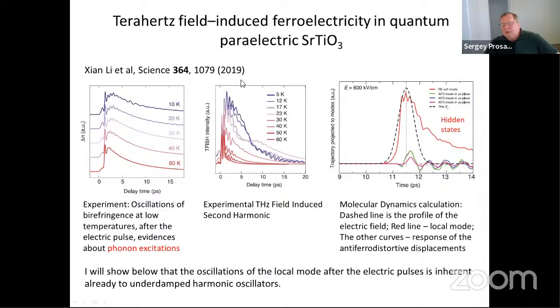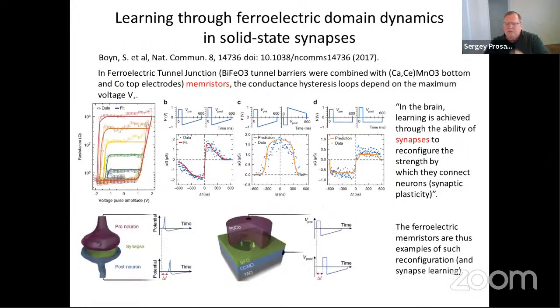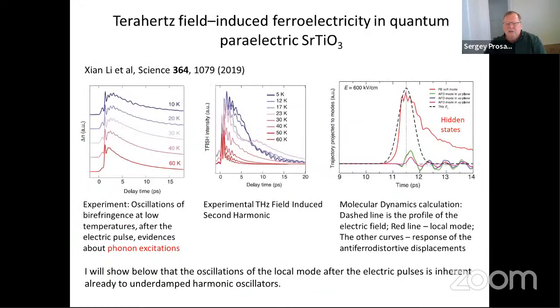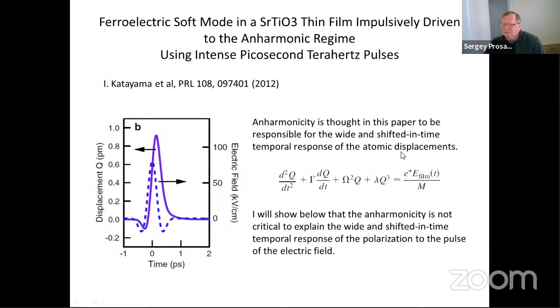But in our case, like in memristors, we apply some limited number of pulses, and we are not in the ferroelectric phase and not in the relaxor phase, but somewhere in between. And in one paper, where was it? It was said that this is because of incomplete switching. You see the point?